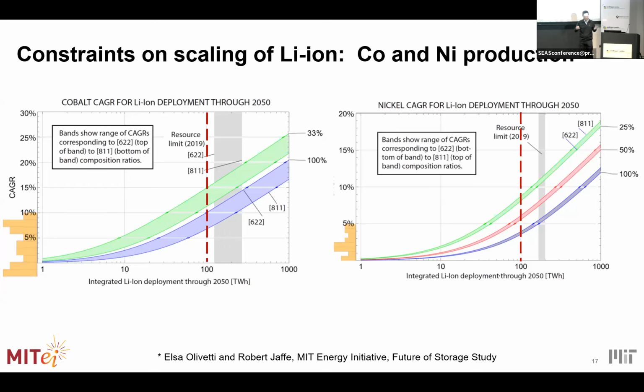So the overall message here is that if we were to do it all with lithium ion, we may actually have enough of each metal, but the amount of production is daunting. And so I assume that for grid storage, neither cobalt nor nickel will be used in the long term. It'll be something like lithium iron phosphate, maybe a manganese-based chemistry. But as long as we do it with lithium, that previous chart will apply.